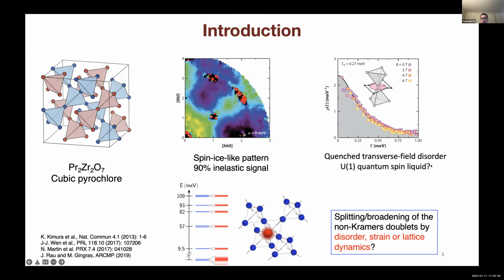the stoichiometric samples. The inelastic neutron scattering result indicates the disorder in praseodymium zirconate can give rise to a distribution of quenched transverse fields acting on the ground state doublet. Some theoretical work also suggests the disorder could induce a quantum spin liquid state. However, the origin and distribution of the disorder is not clear so far, and we know that praseodymium 3+ is a non-Kramers ion, so the crystal field doublets are not protected by time reversal symmetry. So we expect to see the splitting or broadening of the non-Kramers doublets due to the existence of disorder, strain, or some other lattice effects.